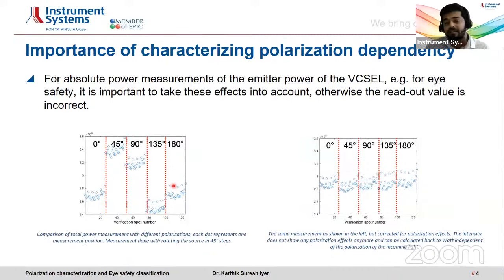This is an important correction that needs to be accounted for, especially for measuring absolute power for a VCSEL, which in turn is very relevant for laser eye safety assessments. Our polarization correction takes place in the form of an inline analysis of the emitted light and corrects the polarization dependency of the entire optical system. This is done through a unique calibration concept that we have developed with the VTC 4000. And bear in mind, this entire procedure is traceable because we calibrate absolute, and it's traceable to national standards.